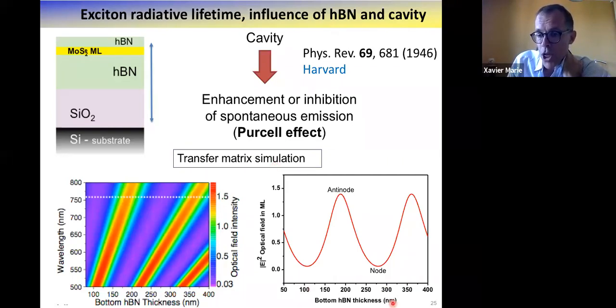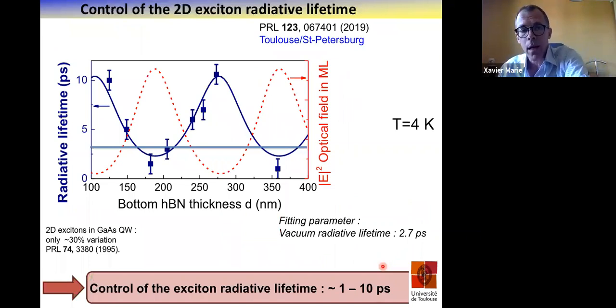So here you have a view. Changing the bottom hBN thickness, you can vary the position of the monolayer with respect to the optical field intensity, either at the antinode or at the node. What do you predict? At the antinode, you predict a very fast radiative recombination. At the node, if this Purcell effect is correct, and it appears in this structure, it's correct for sure, you will have longer radiative recombination. And indeed, this is what we have measured recently, for different samples and many series, the radiative recombination time as a function of the bottom hBN thickness.